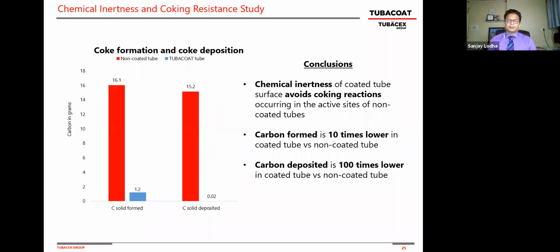So in summary, the chemical inertness of the coated surface avoids coking reactions. Carbon formed is 10 times lower, and whatever carbon is formed, carbon deposition is 100 times lower. So significant improvement both in carbon formation and carbon deposition with these coated tubes.